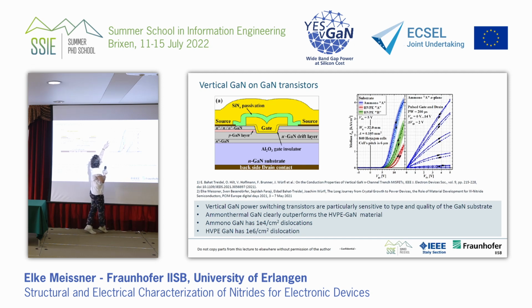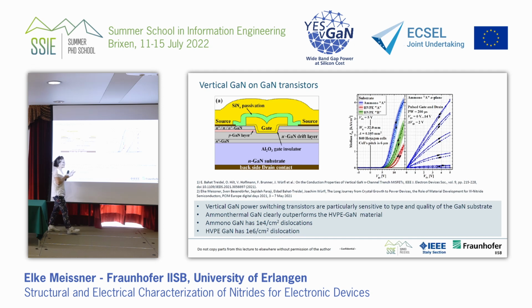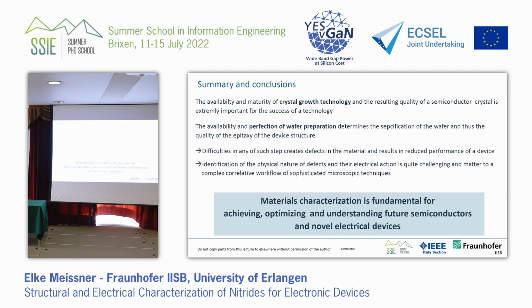And you see that there are 3 types of material, 2 HVPE gallium nitride growth material, and the ammonothermal material. A ammonothermal material has 10 to the 4 dislocations, whereas HVPE gallium nitride typically have something like 10 to the 6 dislocations per square centimeter. And you can see that this performs, I would say, much better in many respects. And there you can see that it's sensitive to the total number of dislocations. And before you saw that it can be sensitive to another dominating defect, like the V-pits. And before you also see that it's a matter of what is the nature of the dislocations and the surrounding, if you have the gathering effect with the carbon.